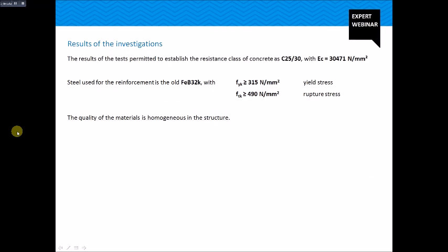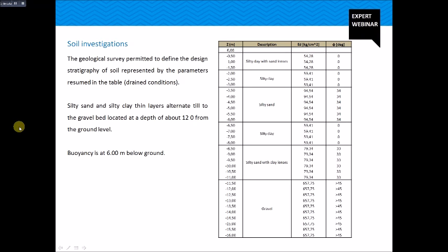The results of these tests permitted to establish, first of all, that the quality of the material is homogeneous in the structure. Then, that the resistance class of concrete is C25/30, while steel used for the reinforcement has a yield stress of 315 megapascal and an ultimate stress of 490 megapascal. The geological survey permitted to define the design stratigraphy of soil represented by an alternation of silty sand and silty clay thin layers down to the gravel bed located at about 12 meters below the ground level. The water table is located at 6 meters below ground.